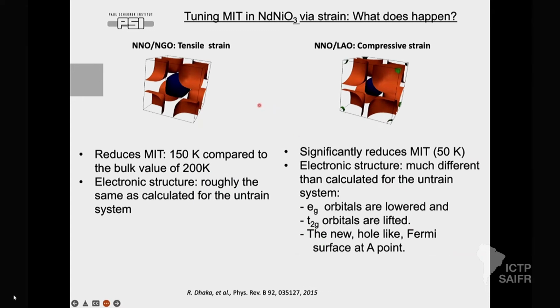So, to summarize this first part of my talk: NNO over NGO under tensile strain, right? What happened there? I said at the beginning that nickelates are strained even without any stimuli; the nickel-oxygen bond is under tensile strain. So if you induce additional strain, the reduction of the MIT will occur.